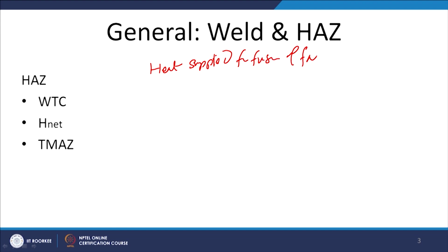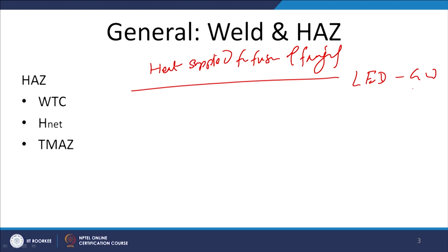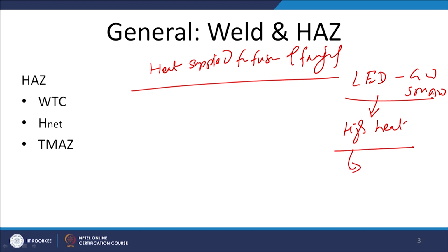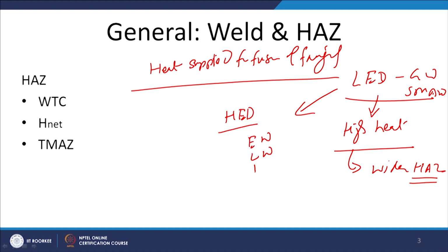fusion of faying surfaces. So, low energy density processes like gas welding or shielded metal arc welding will be supplying a higher amount of heat. So, heat input will be more, and that in turn will lead to a wider heat affected zone. So, in order to reduce the adverse effects associated with the heat affected zone, it is always favorable to work with high energy density processes like electron beam welding, laser welding or plasma arc welding. These processes will require lesser heat input.